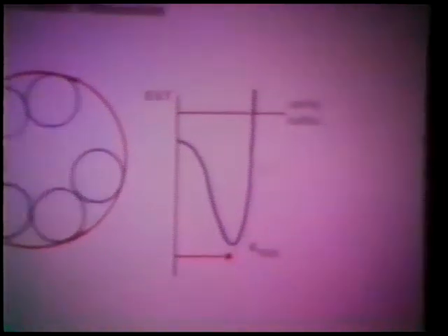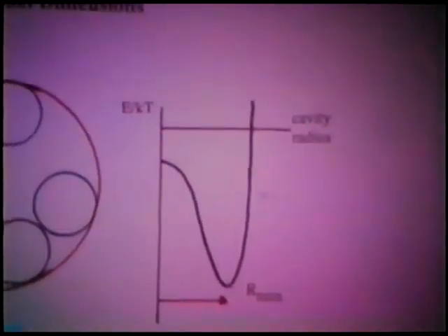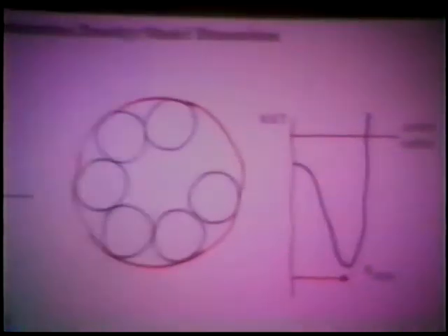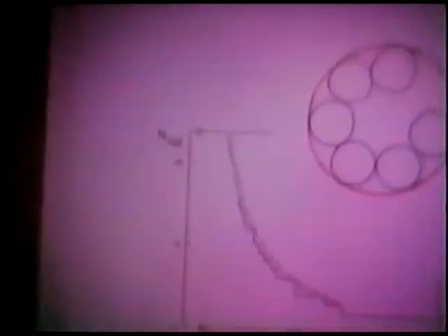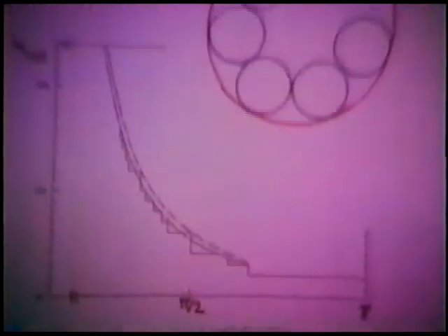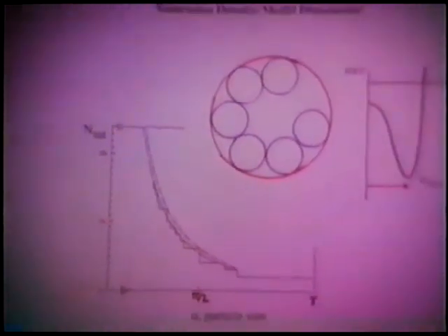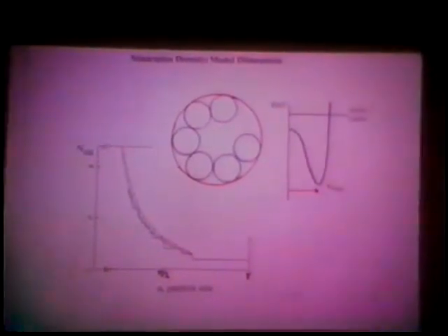Now, there's a way we can make the theory more predictive by introducing one parameter into the system. So far, it's a zero-parameter model. What I've been doing to calculate the size of the absorbing surface is to take the radius at which the minimum in the potential well occurs.